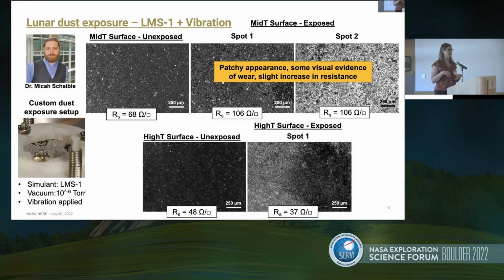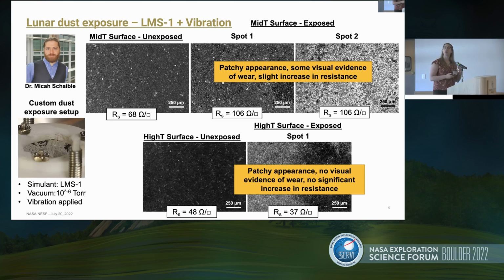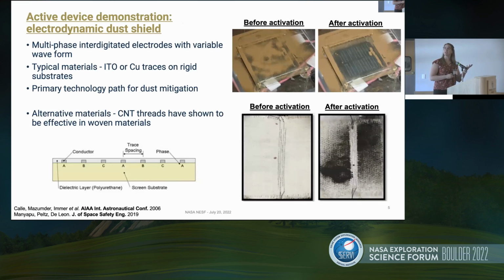And then when we expose it to simulant, we see very little, a statistically insignificant change in the surface resistivity and less dust adhesion after exposure. So this is an encouraging result. But like I said, these surface resistivities are orders of magnitude more than what we would need just for static charge dissipation. So we took this and we looked at an active device configuration.